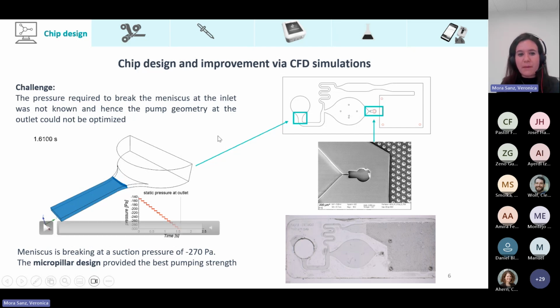We tested several capillary designs to see which one provides a good pumping strength, and we achieved the best results with the micropillar design. Here we can see an image of this microstructure. There we can see the micropillars of 100 micrometers.